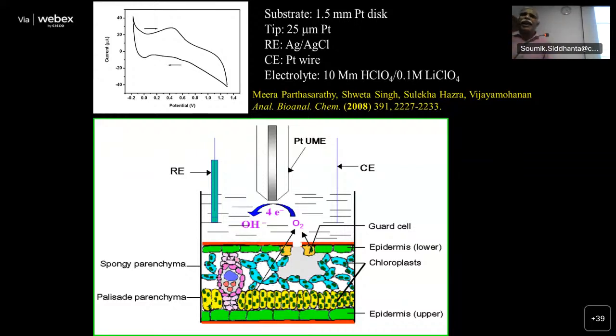When the stomata open, gas exchange happens. So oxygen reduction can be investigated at the stomatal opening. This is a system where a platinum ultra-microelectrode, Pt UME, you can see, is immersed, and then you have a platinum electrode where a stomatal leaf is attached after removing chlorophyll and spongy parenchyma, and this is a guard cell. So oxygen coming out can be detected by using an ultra-microelectrode.